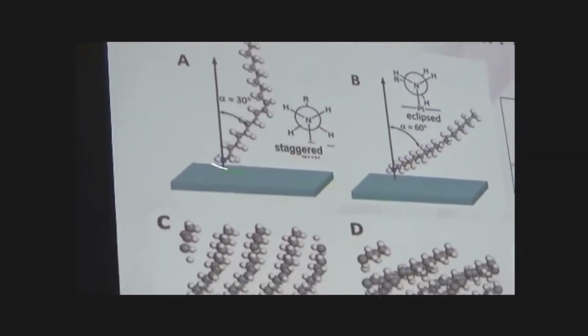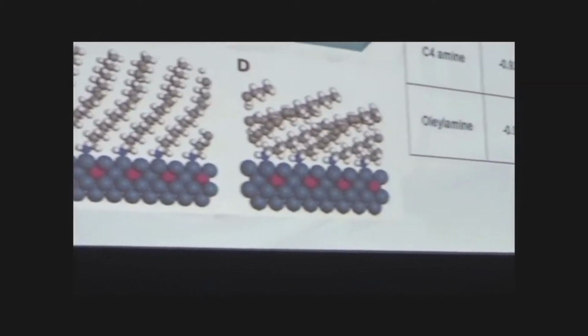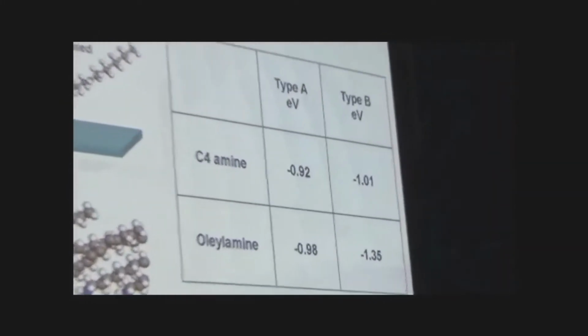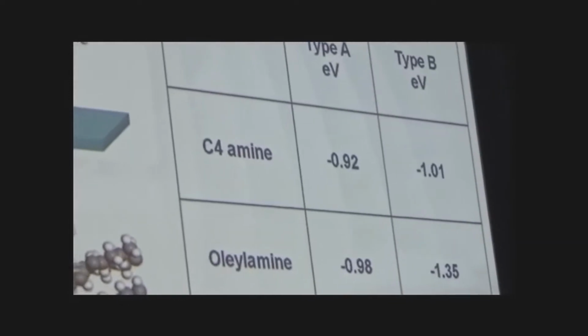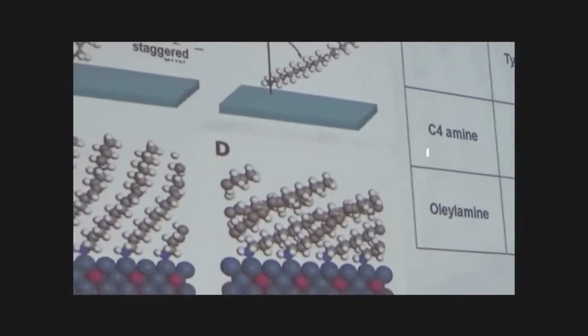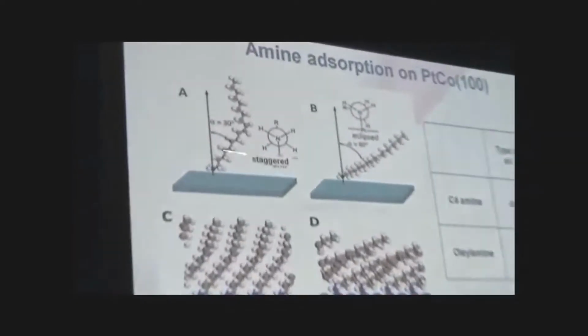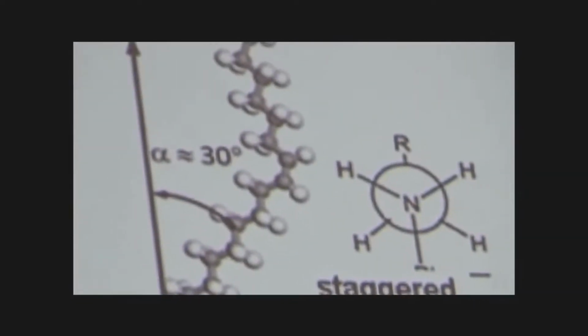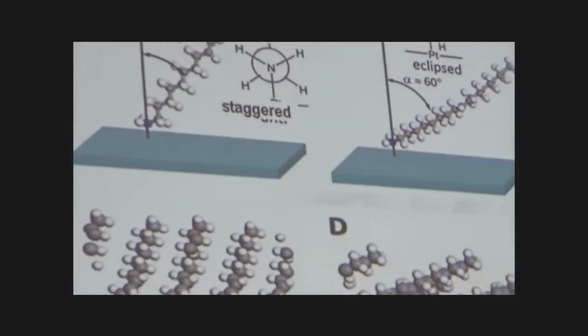Here we have considered two configurations for the organic amine adsorption. The difference between them is the tilt angle. This one is about 30 degrees, this one is about 60 degrees. For the amine with a short carbon chain, the adsorption energy between these two configurations is very similar. But for the long-chain organic amine, this one is a close, compact configuration, so the adsorption energy in this configuration is more stable than this one.